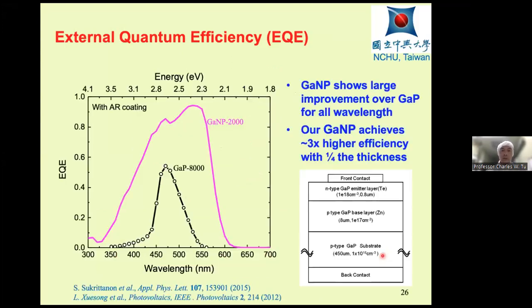And so if we compare this dilute nitride with gallium phosphide, we see that the external quantum efficiency is much larger. So it just shows that we have a direct bandgap material, we have better absorption efficiency, and then we need only 1/4 the thickness.